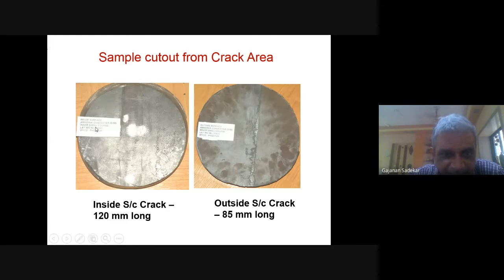So these are the samples taken. Inside, the circumferential crack was around 120 millimeter long, and outside the same crack was looking like 85 millimeter long. This means the crack has started from inside, it has not gone fully, it went only for 85 millimeters. Okay. So these are the photographs of the crack sample which you had taken.